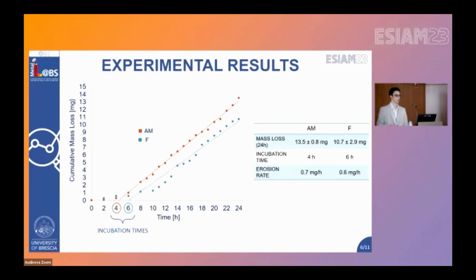And here are shown the mean results of 2 tests for each kind of sample. The data are expressed as cumulative mass loss versus time. And as you can see, several hours were needed just to start the erosion process, and this time is called incubation time. And here is the first main difference. The additive sample had a 2-hour shorter incubation time. But after that, the erosion rates were pretty similar and low.